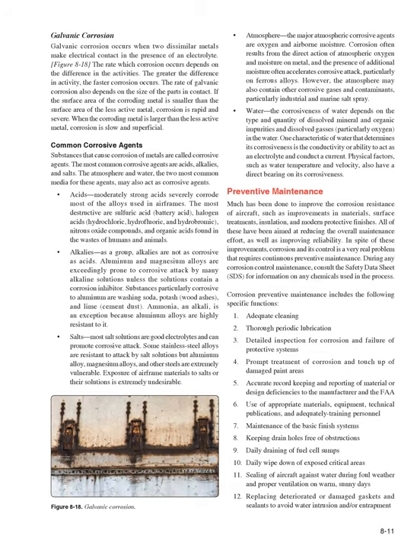Galvanic corrosion occurs when two dissimilar metals make electrical contact in the presence of an electrolyte. In Figure 8.18, the rate at which corrosion occurs depends on the difference in the activities. The greater the difference in activity, the faster corrosion occurs. The rate of galvanic corrosion also depends on the size of the parts in contact. If the surface area of the corroding metal is smaller than the surface area of the less active metal, corrosion is rapid and severe. When the corroding metal is larger than the less active metal, corrosion is slow and superficial.